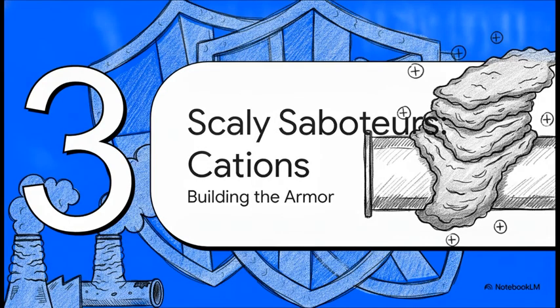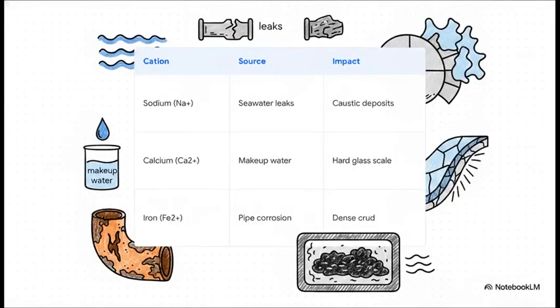Which brings us to Section 3, scaly saboteurs, the cations. The crucial thing to understand about cations is how they physically armor themselves onto metal surfaces. Look at sodium. Whether it gets in from seawater contamination or slippage from your demineralizers, sodium loves to combine with chlorides and hydroxides. The result? These sticky, highly corrosive, caustic deposits right on your turbine blades.